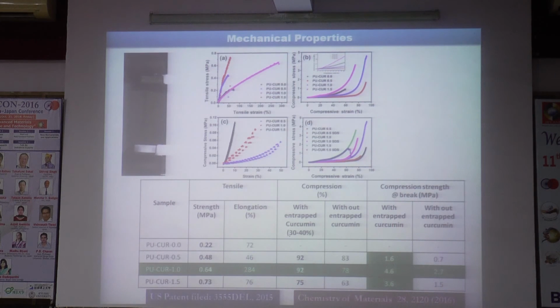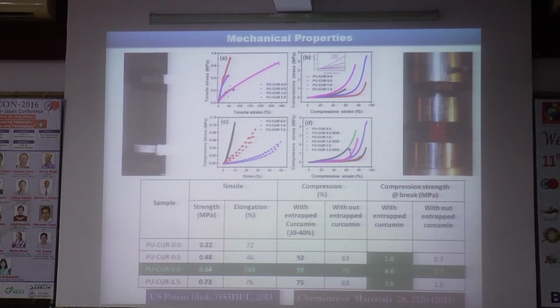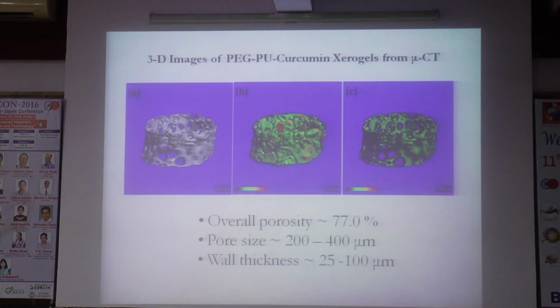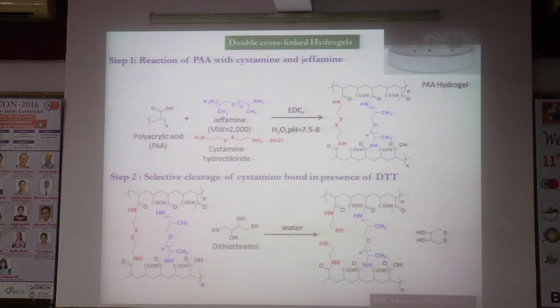So we have seen very good amalgamation here, and we also have very nice compressions of these materials, and we have measured the overall porosity. It is 77%, with a pore size of about 200 to 400 microns, and wall thickness is about 25 to 100 microns. Of course, we can change these dimensions. Last week this paper got published.